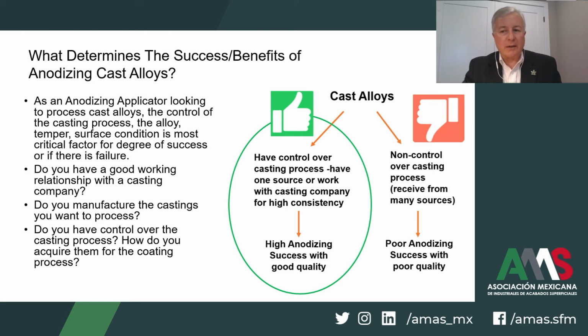If there is no control over the casting process or even input to the source of the casting that will need to be anodized, there will be inconsistency, quality, and other issues that will cause unacceptable results from the anodic oxide layer. So what does that mean? For a job shop applicator, it will be very challenging to consistently produce very high quality on cast alloys without some close relationship to the cast alloy manufacturer. As an example, receiving some 7xx cast alloy from 2 or more casting sources might require some modifications to the stage 1 surface prep. And as shown previously, there might need to be some additions of chemistry to make the process more successful. This is why consistency of the castings are critical to the quality performance.